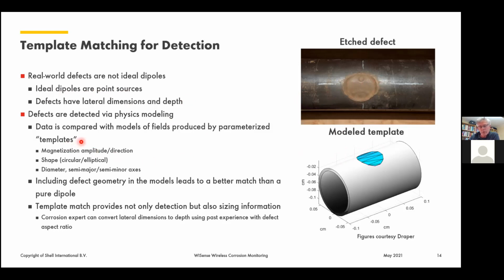And when a patch is developing a detection of a magnetic field, then the algorithm starts to try to match a certain defect template with the measured field. It is going through thousands and thousands of model templates, trying to optimize the match between what it actually sees and what is in the database of templates. And this leads to a very good detection.